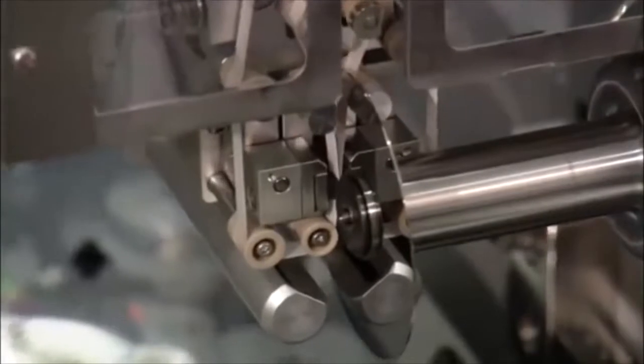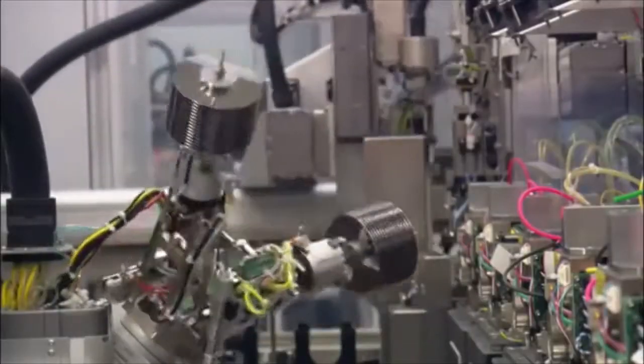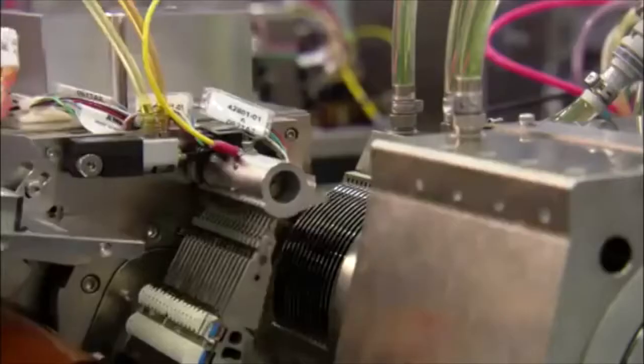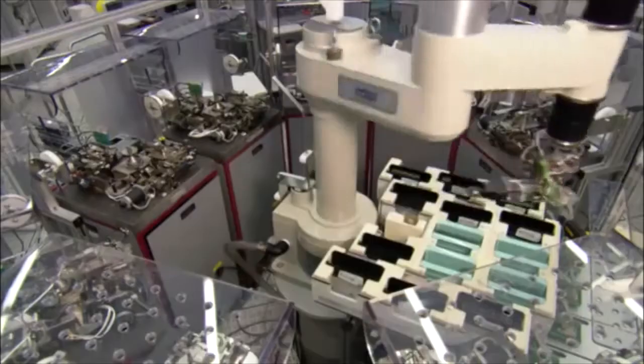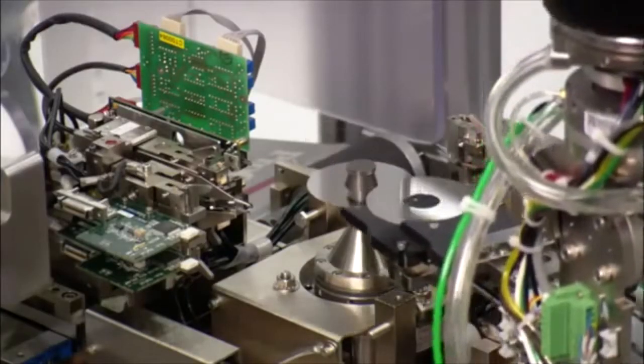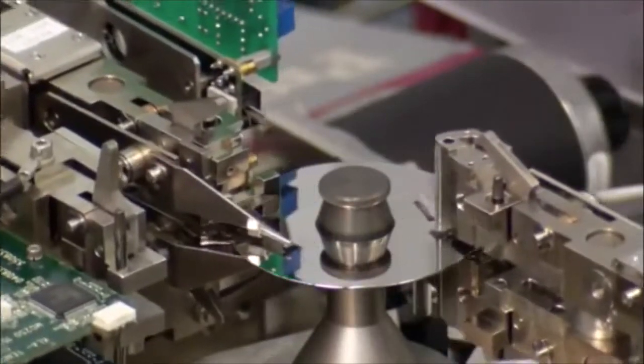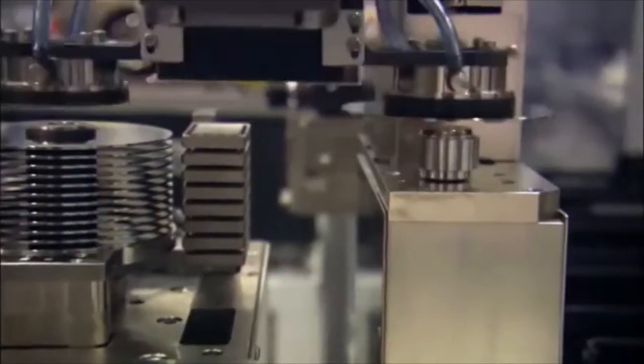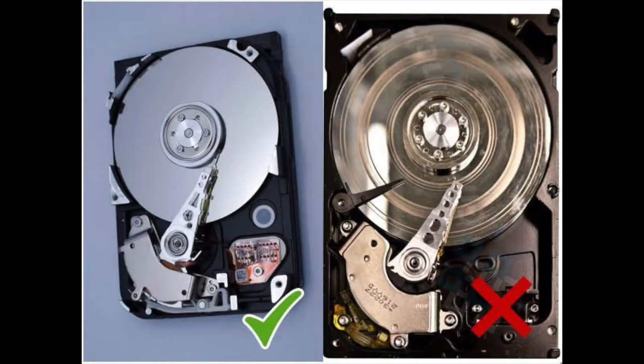A thin layer of chromium is added on top of the aluminum blank right below the magnetic layer. This helps to reduce cobalt's susceptibility to interactions between the magnetic fields of the sectors in that layer. The magnetic layer is then added, followed by a two nanometer thick carbon overcoat. This carbon allotrope is very hard, offering protection against scratching to the surface of the disk. Any abrasion to the disk, and more specifically the magnetic layer, could result in a significant amount of data loss, making this carbon overcoat important to the functioning of the hard drive.